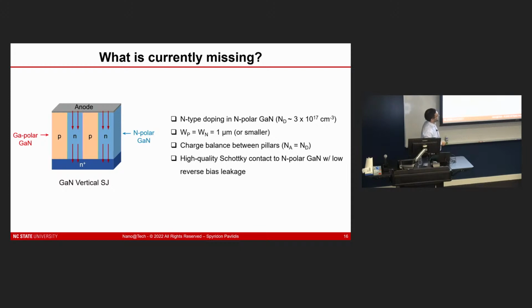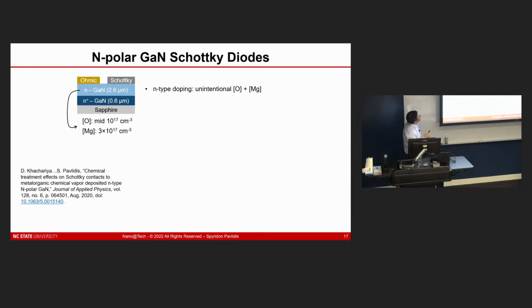And we want to think about Schottky contact engineering so we have low reverse leakage currents as well. So for nitrogen polar Schottky diodes, this is one of the first papers that we published in my group. We worked with Ramon and Zlatko, who grew these N-polar regions, and then we went ahead and made Schottky diodes on these devices. And the goal was to demonstrate mid 10 to the 17 doping.